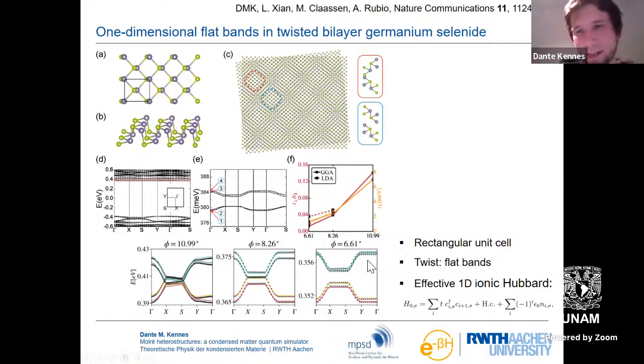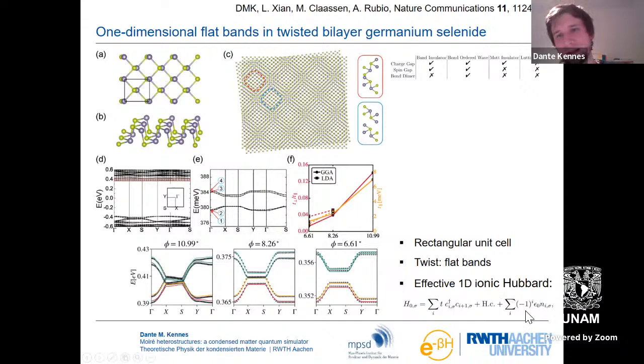Now, realizing this system, and remembering that we of course also have interactions, we classified the physics of this one-dimensional Hubbard model, with a Hubbard type of interaction. And it's quite rich, actually. So you have in this model access to four different phases here, which are classified in this table up here by the presence or absence of charge or spin gaps and whether you have a spontaneous bond dimerization. So in some of these cases, this bond dimerization means that you have a spontaneous dimerization of the bonds. So you make a sequence of strong bond, weak bond spontaneously by the interaction.